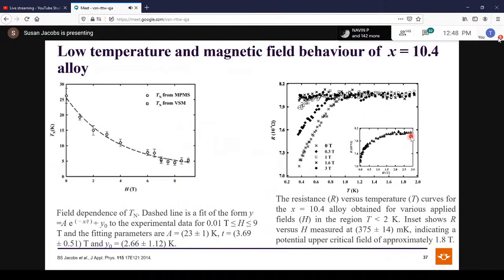This is the last measurement that I would like to share, or the last result. Because the 10.4 alloy is very close to the quantum critical point, which we saw was 10.5, we can push this to quantum criticality using magnetic field as a tuning parameter. So we do see a suppression in Tn up to about 9.5 Tesla. We only measured up to 9.5 Tesla. We need to extend this to see if it actually does suppress to 0.